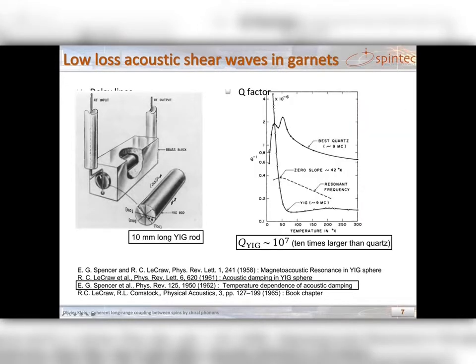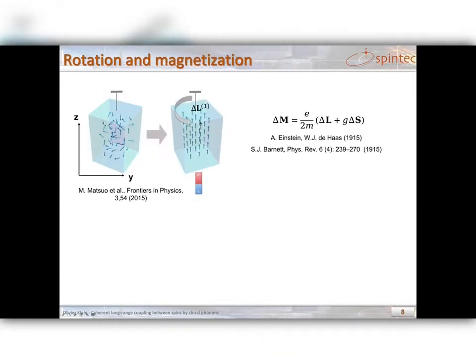So what it shows is that the Q factor, the quality factor of acoustic wave in YIG can be very large. It is actually 10 times larger than the best quartz. So let's go back to the magnon-phonon interconversion. And one question is, what is the physical mechanism behind?